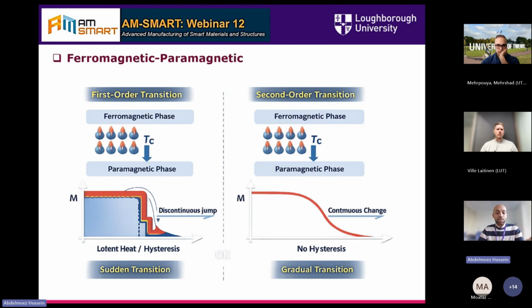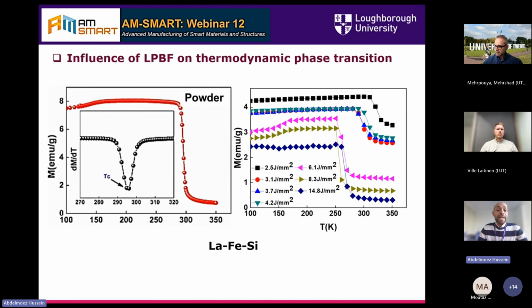For the first order transition, this drop in the magnetization is sharp and discontinuous, and it's associated with a latent heat, which gives us the applications that we need. In contrast, the second order has a very gradual transition and no hysteresis, which is probably associated with very low temperature, which is not required for our application. We need a material that, when we apply a magnetic field, can have a first order transition, so we can have a high temperature response.